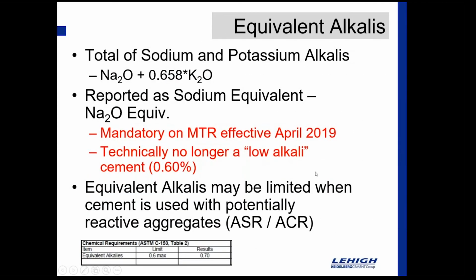Okay, in terms of equivalent alkalis, there's the table at the very bottom of the mill test report, and that's a measure of the total of the sodium and potassium alkalis that's recorded as Na2O equivalent on the mill test. Effective in April of 2019, ASTM made that mandatory on all mill tests to be reported. And what you found at that same time is that technically there's no longer a low alkali cement. We used to say 0.6% and lower in terms of equivalent alkalis was a low alkali cement. That's because at one point in time, we assumed that controlling the ASR, the alkali silica reactivity, used to be kind of up to the cement. If you had a low alkali cement, then a lot of folks thought you were good to go.